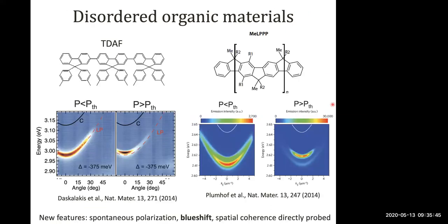A few years later, polariton lasing was shown in two amorphous materials. Our work focused on this trimer of methylphenylfluorene called TDAF. Below are just images of the k-space luminescence below threshold and above threshold, where you have this collapse near k equals 0.